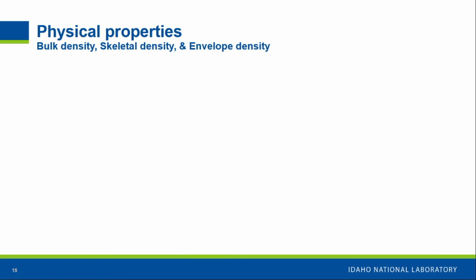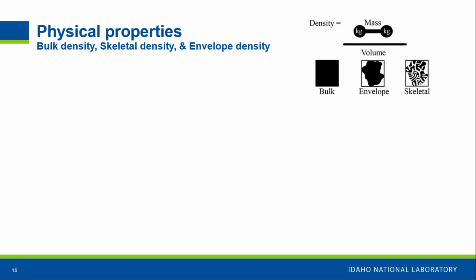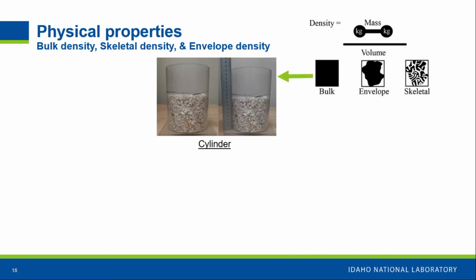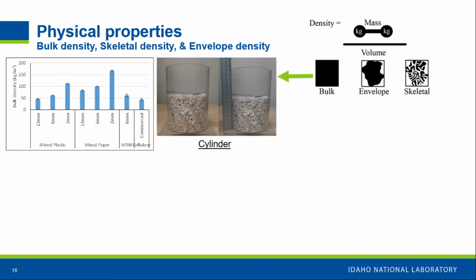So another property we check is the density, which is very important for the insulating material, because it will give you some sort of idea what the void space inside the material will be when you pack them. So we tested the bulk density, and we saw that the bulk density of the material is different, and it varies with the size. When we reduce the size, we increase the bulk density, which makes sense because when we reduce the size, we can pack better. So we can minimize the void space between one particle and another particle.